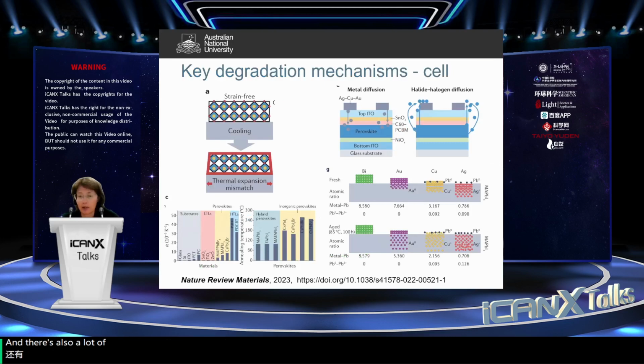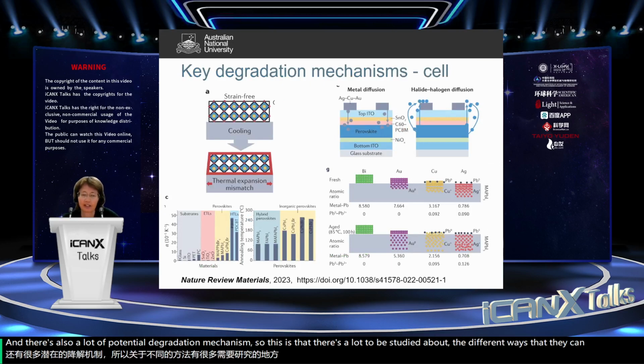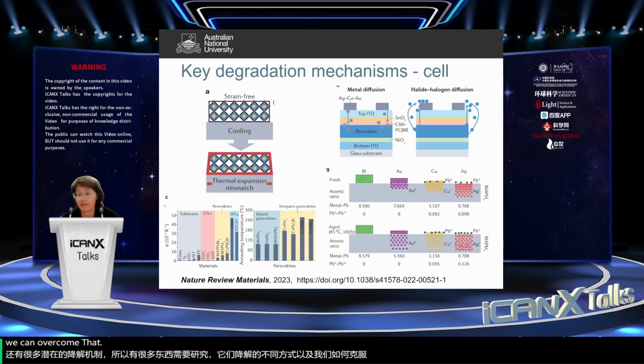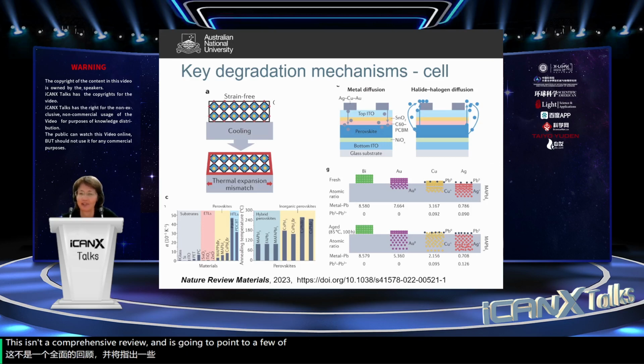And there's also a lot of potential degradation mechanisms. So there's a lot to be studied about the different ways that they can degrade and how we can overcome that. So this isn't a comprehensive review. I'm just going to point to a few of the mechanisms here. One of the mechanisms is the strain in the perovskite. So you form the perovskite usually at a temperature of 100 or so degrees, and then it cools, of course, and you have a thermal expansion mismatch with your substrate. And you can see on the graphs at the bottom left that there is a big mismatch, especially between hole transport layers and other materials, but also between all the different parts of the device.